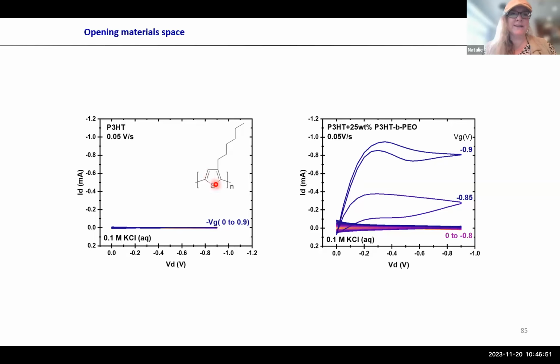P3HT. So we made a comparison and made an OECT with P3HT, again in aqueous solution. And you see whatever we do, so we apply different gate biases, you have zero modulation of your source drain current, which is not surprising. It really just doesn't work. But once we do the blends, I would not call them super nice OECTs, but you see, once we do blends, we can actually get P3HT working in an aqueous potassium chloride electrolyte. So that really gives hope that we may not always have to redesign a lot of the polymers,